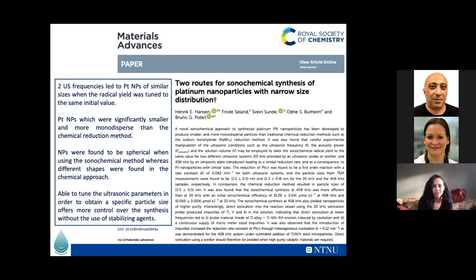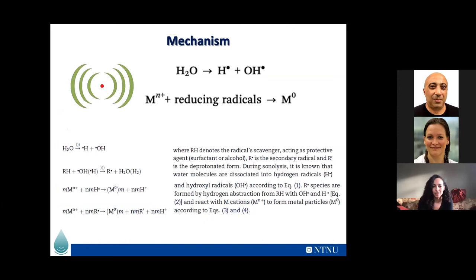We also did some sodium borohydride experiments without ultrasound, and we got in the region of 3 nanometers. But we also found that all the nanoparticles produced sonochemically were spherical in shape, which was different from the chemical approach. We also found a more monodisperse distribution of the platinum nanoparticles than with the chemical reduction methods. So that was good. We actually put forward in that paper that the H-dot acts as a reducing agent. So if you're using chloroplatinic acid, for example, then it goes straight into your platinum nanoparticles.